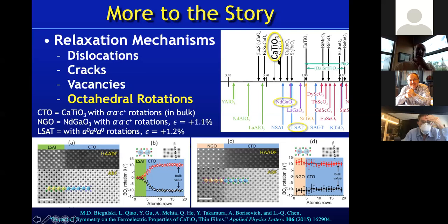And this example of calcium titanate is a nice example because it points out what happens when you rain the same material down on top of two substrates that you would think are going to give rise to very similar strains. In the one case, on neodymium gallate, you'd expect a biaxial tension of 1.1%, and in the case of LSAT, 1.2%.